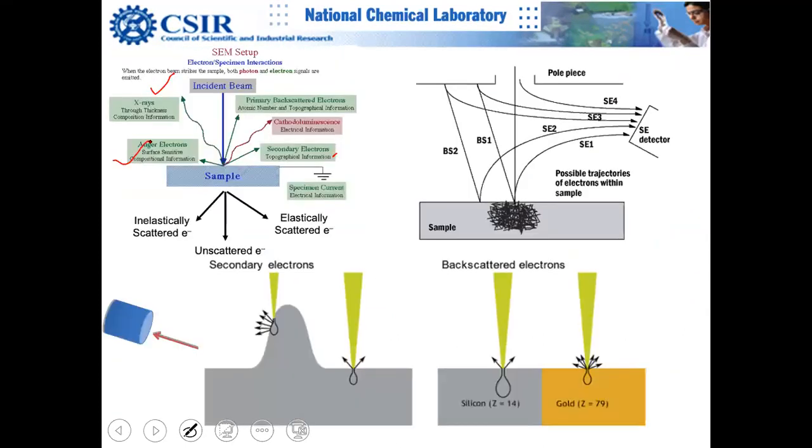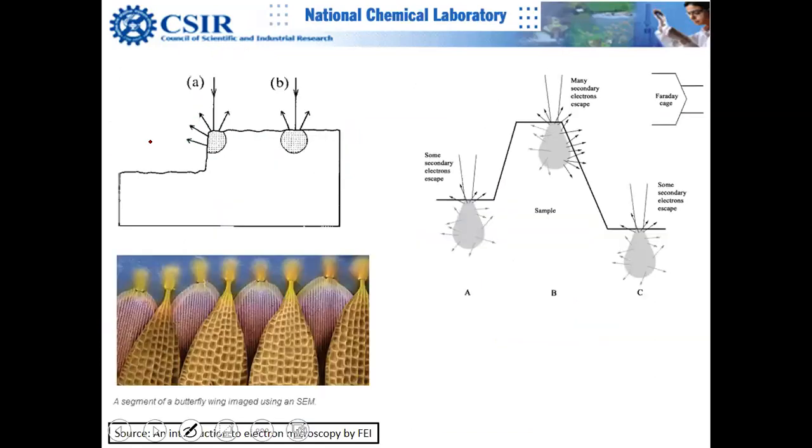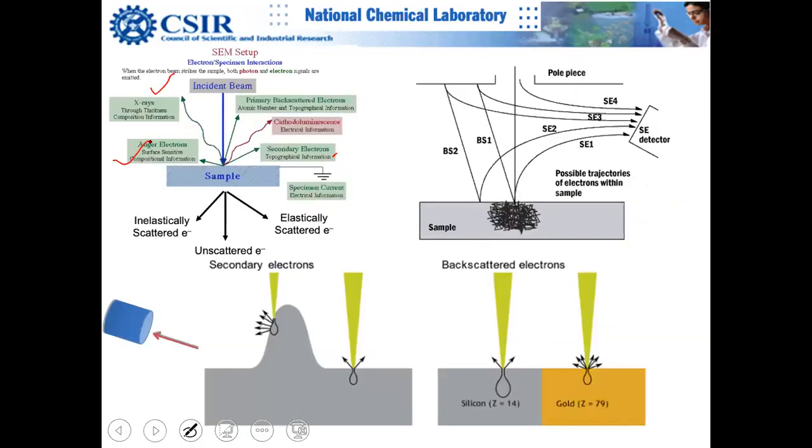This one, right? So here you detect the other electrons. So Auger electrons and X-ray photoelectrons are highly surface sensitive. What this sentence means is that they give you information only for a few nanometers. When I say few nanometers, I would say 2-3 nanometers maximum.